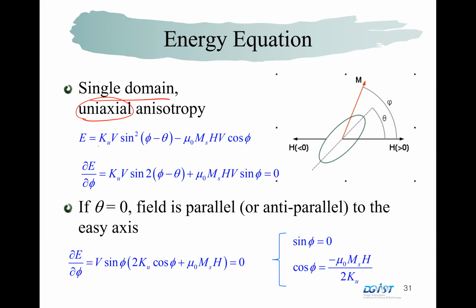So here, to describe the initial anisotropy energy, I'm using Ku sine square of theta instead of minus Ku cosine square of theta. These two equations, as we already mentioned, are mathematically different, but physically the only difference is a constant. So for the energy description, it's identical. But for some reason, we are starting with the sine square. And as we mentioned, this Ku, anisotropy energy, is actually the energy density. So we need to multiply by the volume of your system to obtain the total energy.